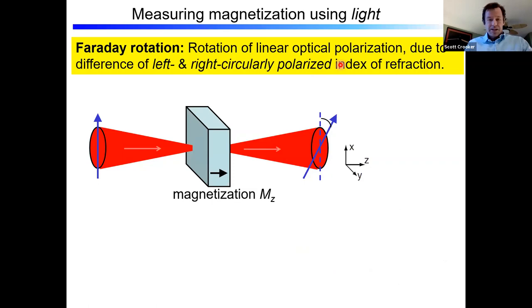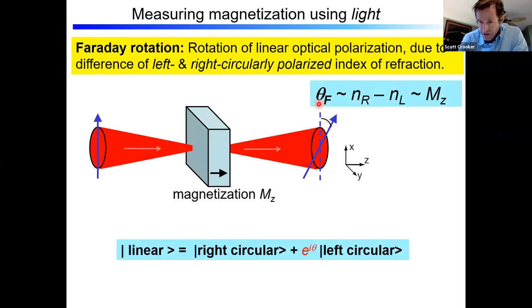So there are many ways, of course, to measure magnetization. In our group and in many groups around the world, we do it using light. And in particular, most of our methods are based on optical Faraday rotation or optical Kerr rotation. So again, if you remember your optics class, what this refers to is we have a linearly polarized beam of light and we pass it through some magnetized material or some material with a non-zero spin polarization, then that linear polarization will become rotated by some small angle, and the amount of that rotation is going to be proportional to the magnetization. And this typically derives from the difference in right and left circular polarizations. That's what gives rise to a Faraday rotation. And that occurs in materials that break time reversal symmetry or that have some finite magnetization.